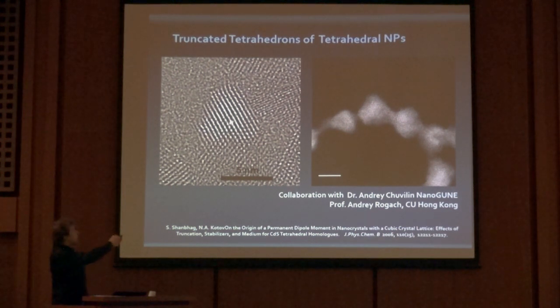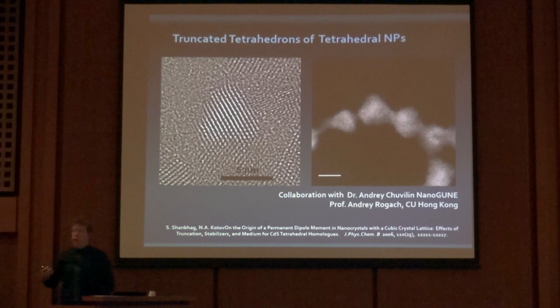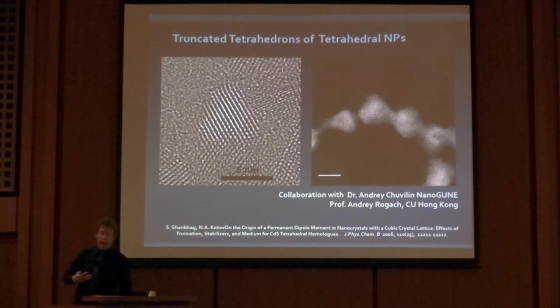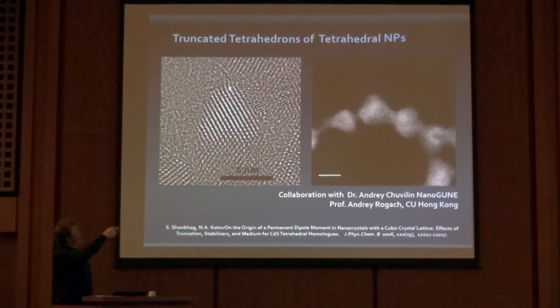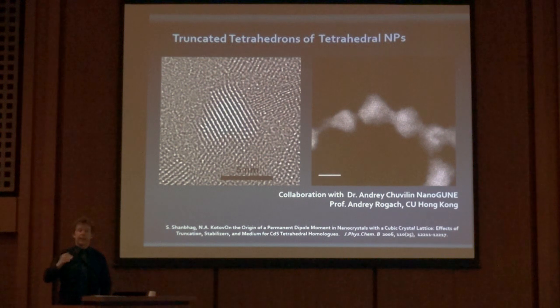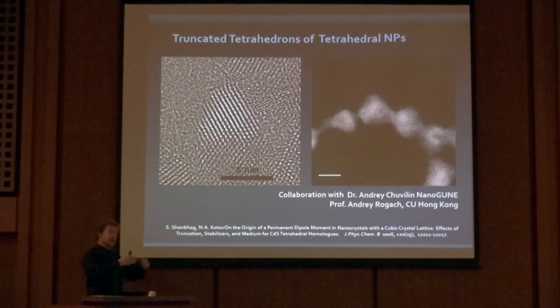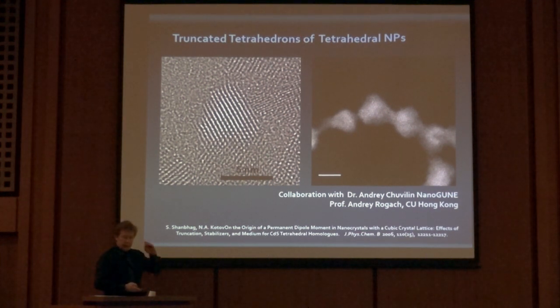First, I'd like to point out that if the particles are tetrahedral, they are chiral if the tetrahedra are imperfect. And imperfections of tetrahedra are actually very much built in the synthetic chemistry of the nanoparticles, because the apexes are truncated. They have high energy, and therefore they're not energy efficient if the particle is formed with these apexes. And so, additionally, there is a chirality on the surface and chirality of the crystal lattice.